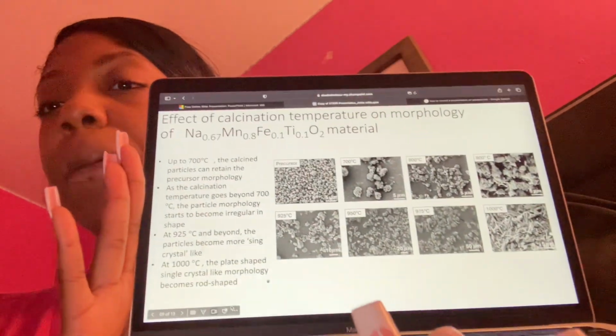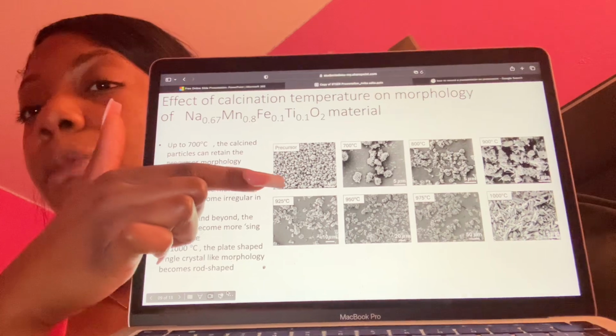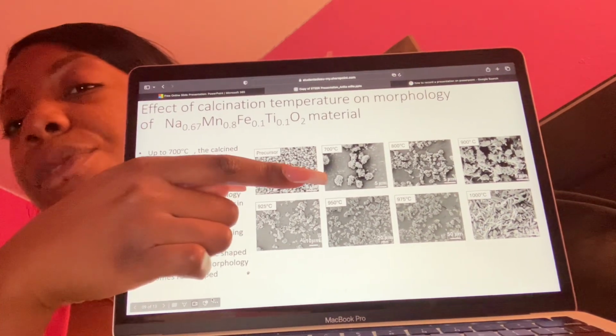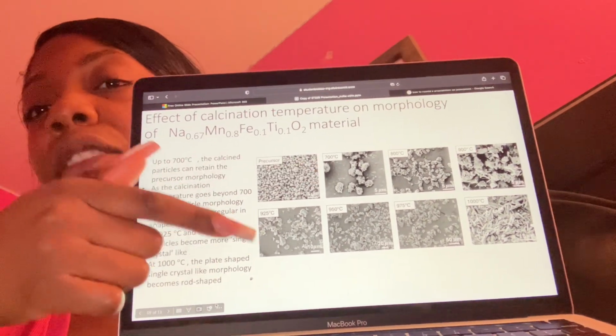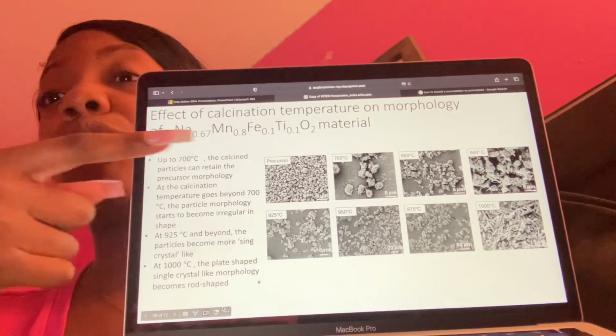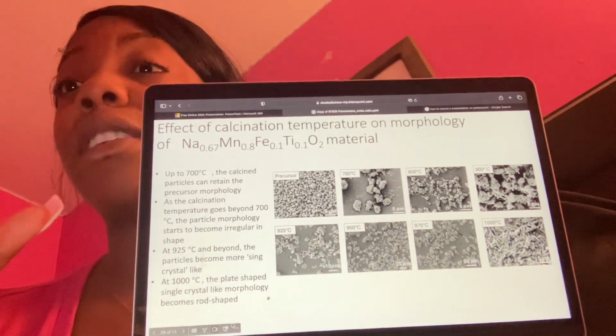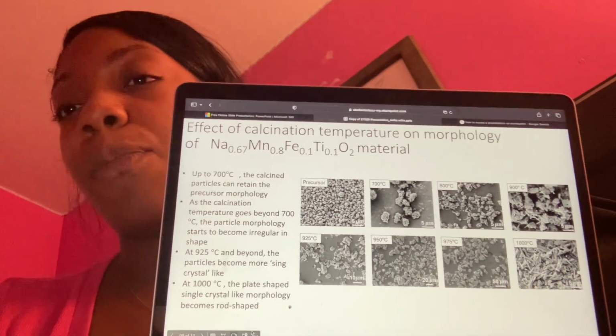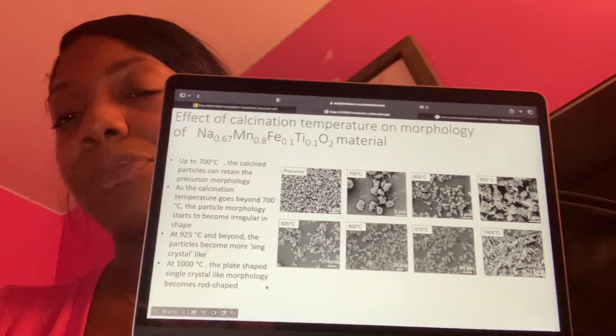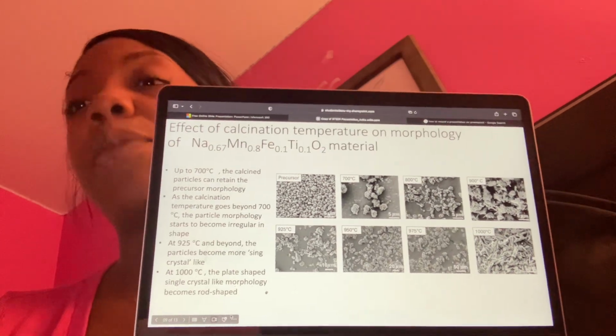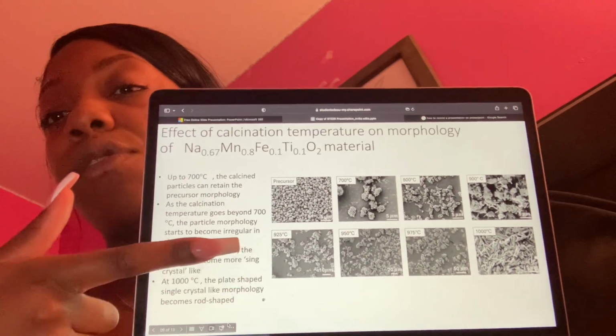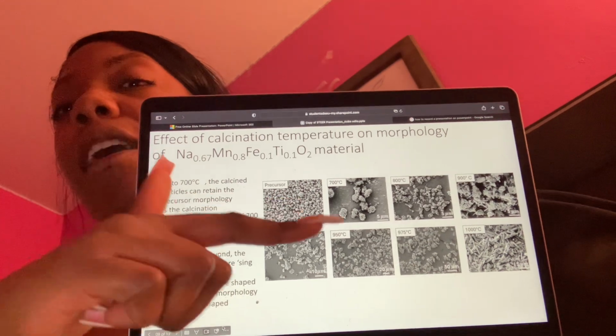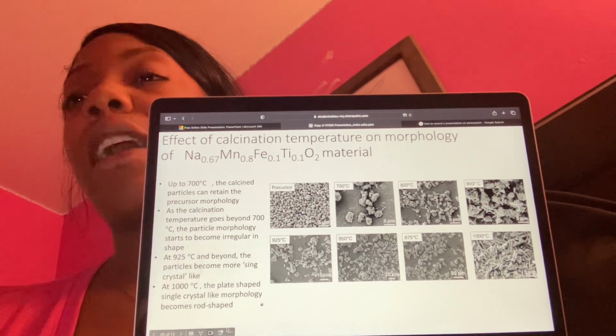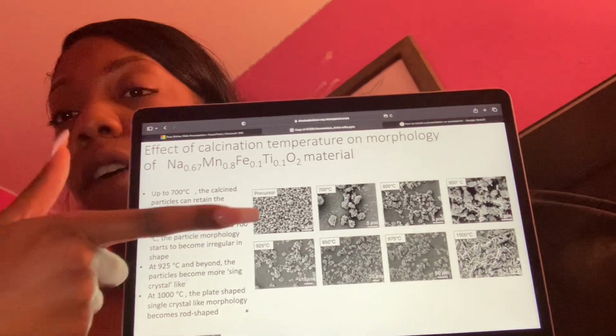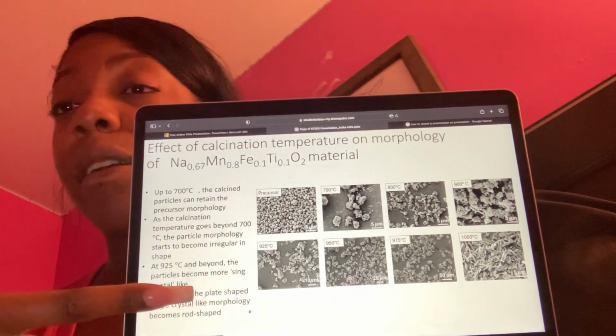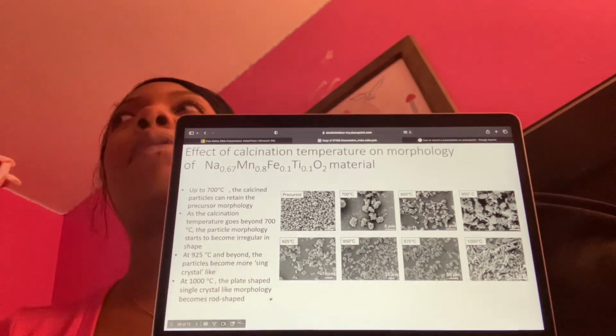So as you can see, this is our original morphology in the precursor, and as low as 700 degrees. All of these are the temperatures we used during the calcination process. This is where we dry the product and get it down to a powder to then slurry cast to make our electrodes. As low as 700 degrees, it's able to retain that original morphology, but as you get higher in temperature, it loses that morphology and it becomes rod shaped.